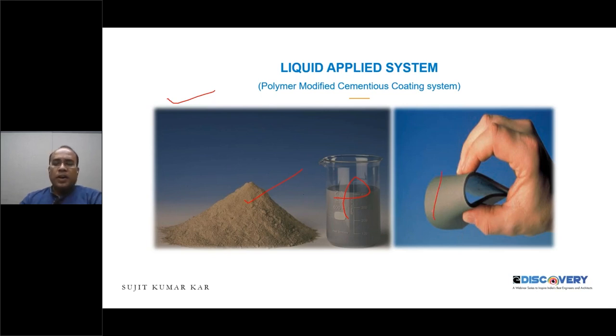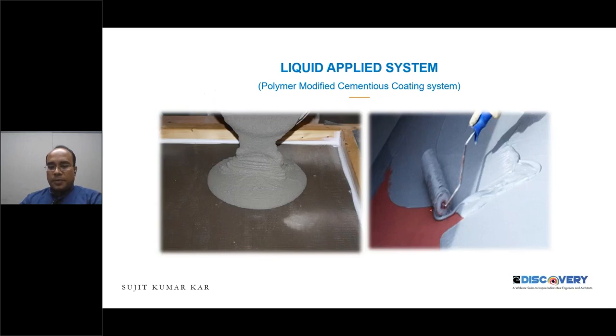It is able to provide 1 mm to 2 mm thickness, depending on the type of material you are using, and this flexibility is very high, and it is able to do crack bridging up to 1 mm. Now, this is the way you can use this polymer modified cementitious coating. After mixing this powder with liquid, it looks like this, and once you apply it by brush, it can spread all over the area, and you can take care of all the joints by applying proper joint treatment methodology, and you can get an unbroken film, so that you can get the best benefit out of it. But the only drawback is you cannot keep it exposed for a longer period.